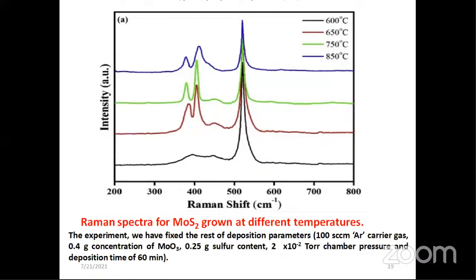As we increase the temperature of the substrate, the FWHM of this Raman spectra increases, and the thickness of the MoS2 layer also increases. At 650 degrees centigrade, we found monolayers, and at 750 degrees centigrade we observed a bilayer type of structure. Above that, at 850 degrees centigrade, we observed multilayer MoS2 films.